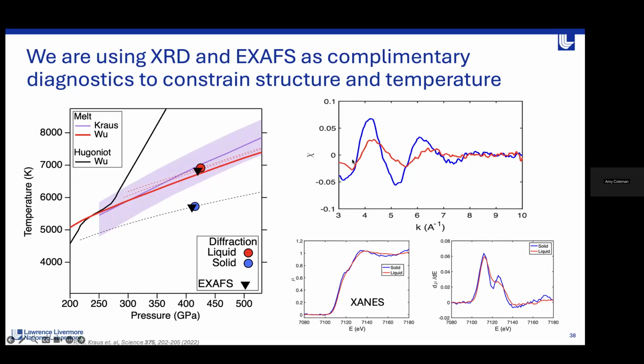One thing we can see that's quite nice is there is a marked difference between the character of solid and liquid XAFS. We can see that in the XANES where there's a difference across the edge, and we can also see it in the differential of the edge itself. So we are able to differentiate in these experiments between solid and liquid XAFS.